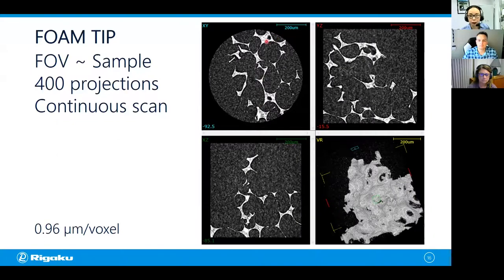You can clearly see the foam and the air. They have very good contrast, but you might realize that those pores in the foam are not round shaped. They're kind of broken. This one looks even worse. When you have a fragile sample like a foam or porous material, and if you cut it down to the size of the field of view, you will be seeing the damaged surface.